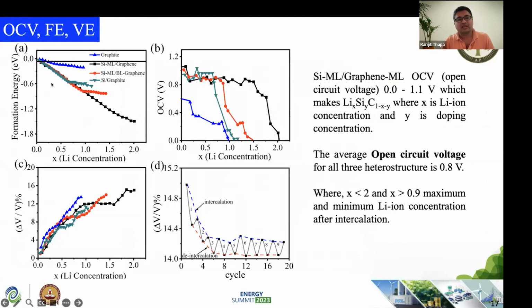And you can see that we have calculated all these things, and it is really coming negative for formation energy. And OCV, you can see this is the graphite. So overall, it is 0.4, which is the result. And when we included the silicon, of course, we can increase up to 2 the specific capacity, but the OCV